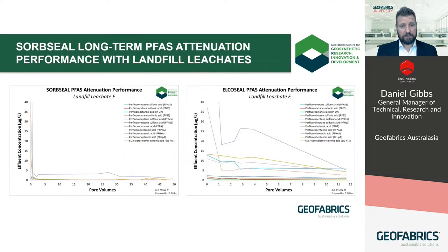Well, that was excellent as well, especially given that, again, MSW landfill leachates are a chemical soup which contain a wide variety of co-contaminants alongside the PFAS. They're all competing for space on the surface of the activated carbon. The left-hand graph shows Sorbseal's ability to strip the leachate of a range of PFAS, both long and short chain, while on the right we can see the performance of a standard unmodified Elcoseal GCL without any activated carbon, showing some attenuation performance, but not nearly as efficient as the Sorbseal product.